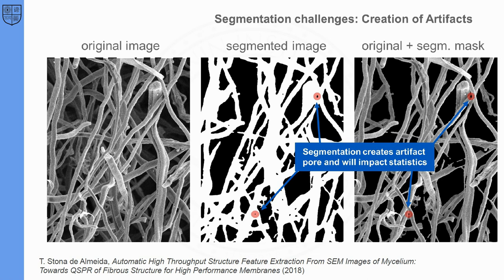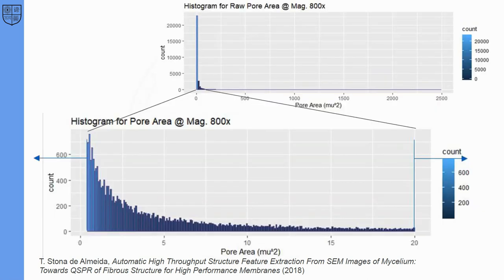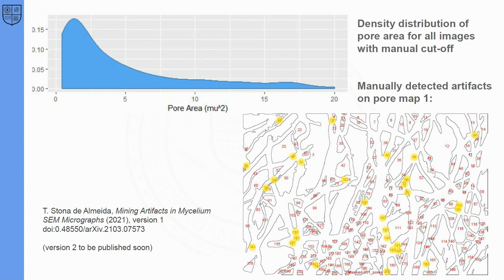The quality of the metallic coating determines the brightness of the image. The automated segmentation can both miss real features and create artificial ones, adding uncertainty to the characterization process. For example, several artificial pores were created by the segmentation — pores that are artifacts of the algorithm. We obtained a distribution of pore area that was very heavy on small pores, excessively small pores below 0.4 micrometers squared. After more detailed inspection, we noticed these pores were near the lower limit of accurate resolution. After several discussions, we decided to set cut-off limits and ignore pores below 0.4 and larger than 20 micrometers squared.